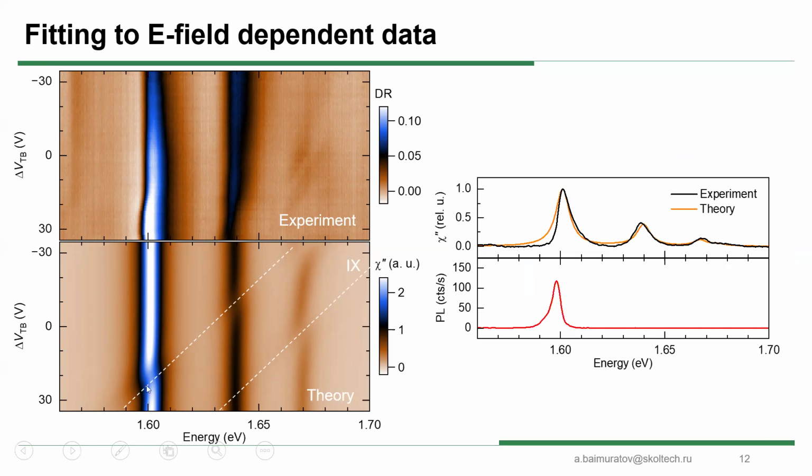We found positions of the interlayer peaks because if you apply an electric field, they will have a slope in this portion, because of the permanent dipole moment. We found this anti-crossing, and M3, this part, will be hybrid. These lines show the change in energy in electric field.